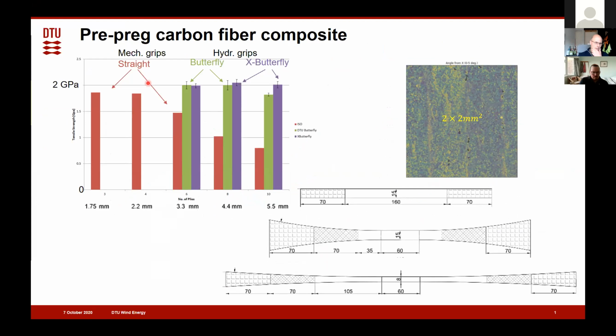So I will actually go down to a very simple case: finding the tensile strength of a UD homogeneously distributed carbon fiber composite. So this is a prepreg. We have 2 studies, one of a prepreg carbon fiber composite and one of a pultruded profile. So you can see the structure is rather uniform, and the color codes here indicate the misalignment going from 0 to 5 degrees. So the composite is really well aligned.